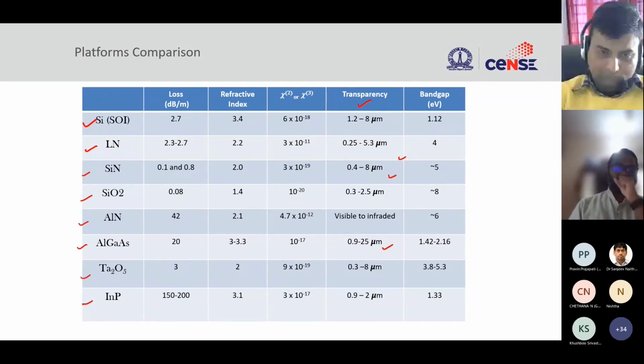Based on these choices, we thought silicon nitride is a better material to work with, right? The reason for that is it has broad transparency, and it is a silicon compound. So you can easily make silicon nitride using the silicon process technology that we have. And it is amorphous in nature. For example, lithium niobate needs to be crystalline to get the required material properties. So silicon nitride can still be amorphous, and we should be able to do photonics with it.